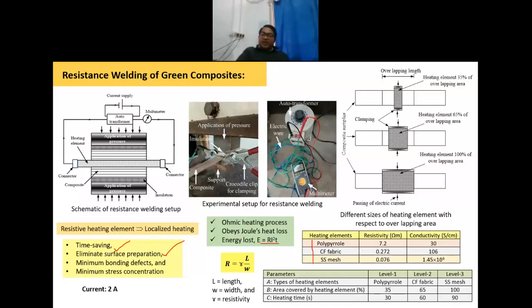Now you can see the corresponding values of resistivity and conductivity. Stainless steel mesh has the highest conductivity among all three heating elements. Carbon fiber fabric has a moderate level of conductivity. And polypyrrole, though it is a conductive polymer, you can see the conductivity value is very low.